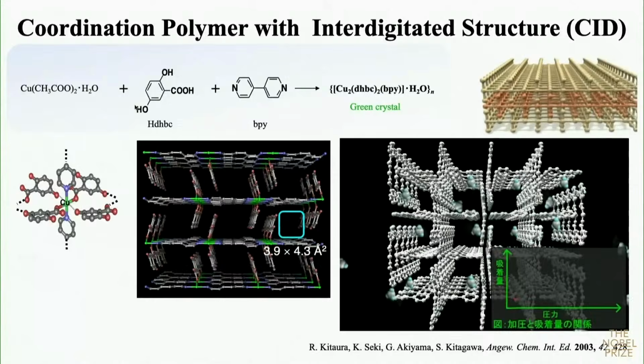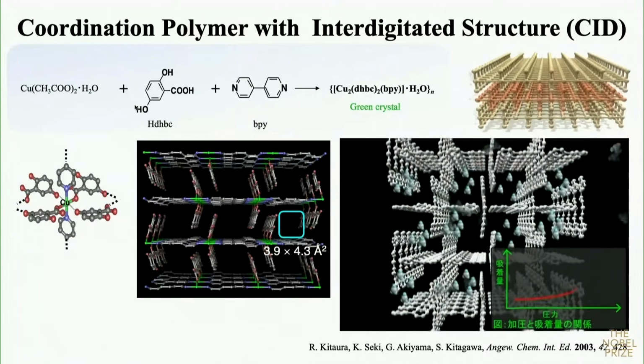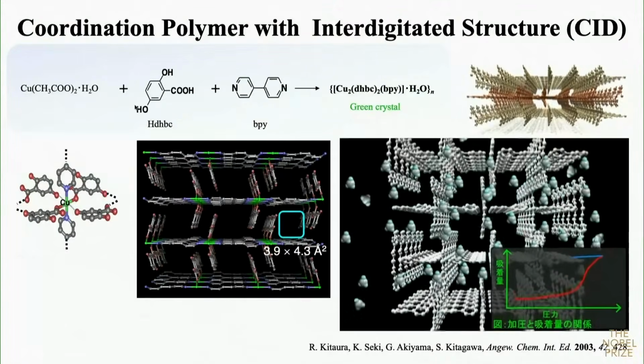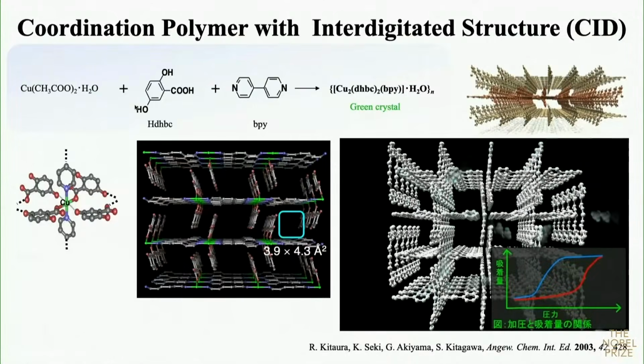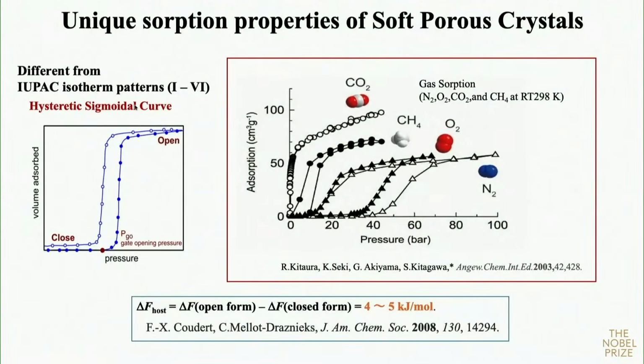One example is our case. We synthesized this kind of system using copper. When gas is introduced, the gate abruptly opens up, and when the pressure is reduced, the gate closes. What is important is that this shows a hysteretic sigmoidal curve, completely different from conventional IUPAC isotherm patterns. So we can distinguish supercritical gas like this at room temperature. From calculation, the energy difference between the open form and the closed form is only 4 to 5 kilojoules per mole. That means this is a cooperative phenomenon.